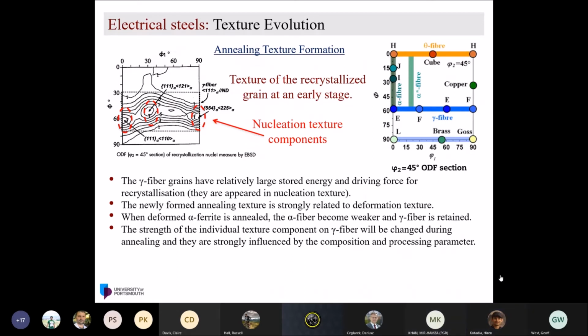these are the points I indicated that are believed to be the nucleation texture from the gamma fiber, and then with further annealing, it will be reoriented or rotated toward the Goss or the rotated cube or cube in the final annealing. So these textures are very interconnected, from the deformation texture to the transformation to the annealing texture. That's why we have to understand the texture evolution during the thermal processing. Next.